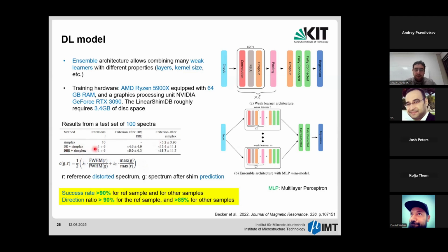For our deep regression, with 1 iteration, 1 acquisition, we already get quite similar enhancement to the simplex after 10 iterations. So we get around 4.6 enhancement. And if we add the simplex after that, we can get more enhancement. So we get 15 times enhancement in the line width and the magnitude, telling us that this deep regression model helps the simplex to avoid getting stuck in local minima. And the other model, the deep regression ensemble, has more or less the same performance. So we do not see a significant difference between the two, but both of them show that in 1 acquisition they can already get to the same quality as the simplex for 10 acquisitions, and they can both help the simplex afterwards to avoid local minima and get further enhancement.